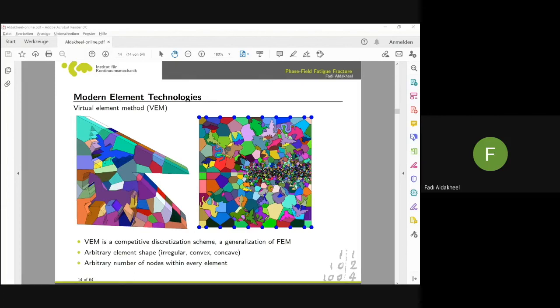Well, see, if you have no information about your last question, about the length scale, how to use this length scale. If you have no direct experimental data, which you can really use to get this particular fracture length scale, which is the transition between the intact and the fracture zone, you can do the following. Just have it, first of all, as a material or a geometric parameter. Look at your discretization, check the length of one element, and multiply it by two, and this is your length scale as a first shot, and run the simulation.